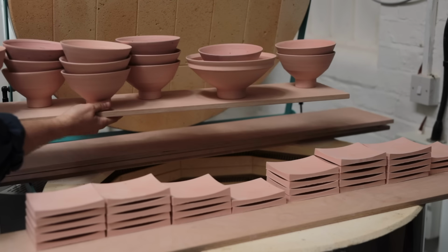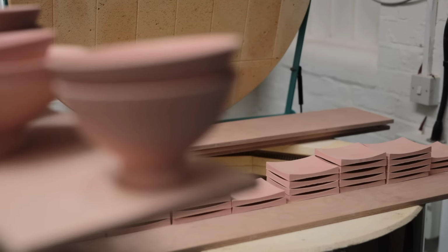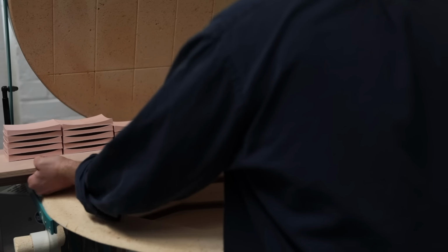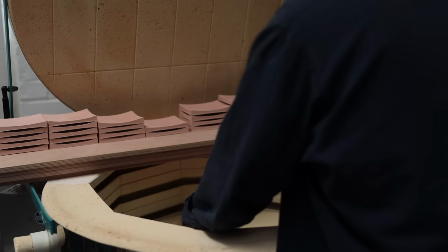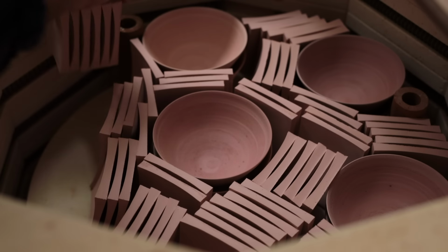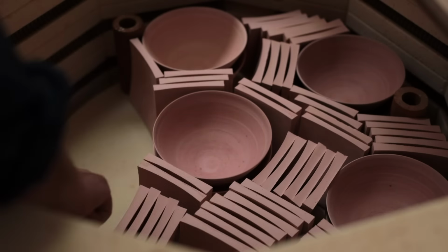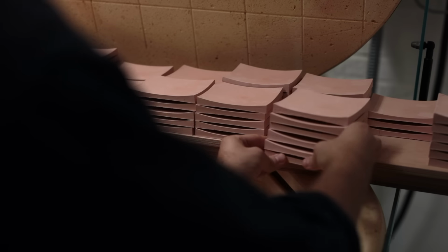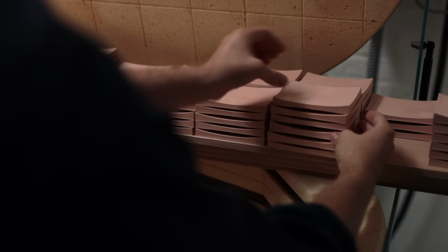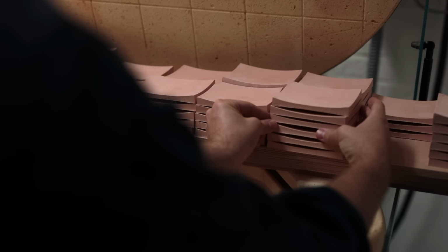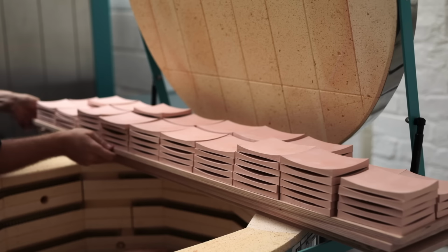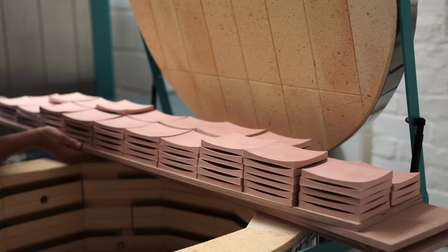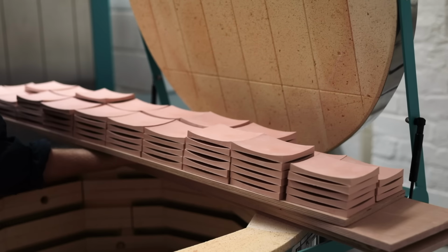These all come in powdered form and are mixed thoroughly into the water, and when these absorbent little dishes are dunked into the glaze, the water itself is rapidly absorbed into the clay body, leaving a layer of the raw materials on the outside of the pot. The longer you leave them submerged, the thicker the layer of glaze will be, but you can quite easily completely overwhelm the clay. Dunk them for too long, oversaturating them, which results in the glaze flaking and cracking off before you even fire them again.